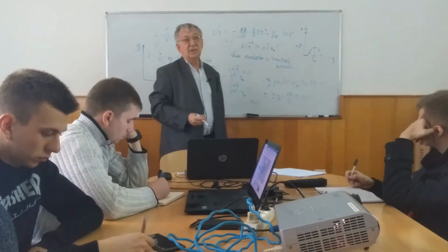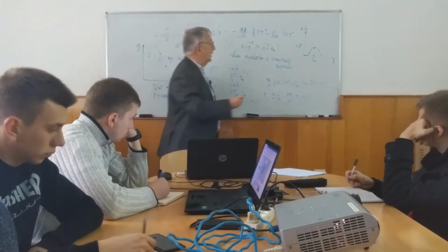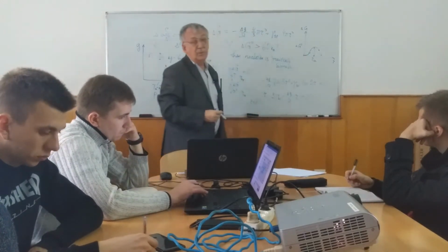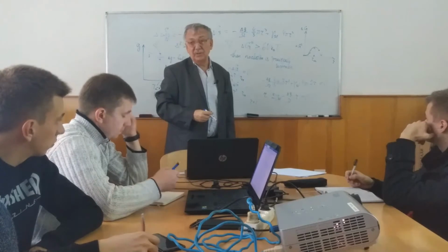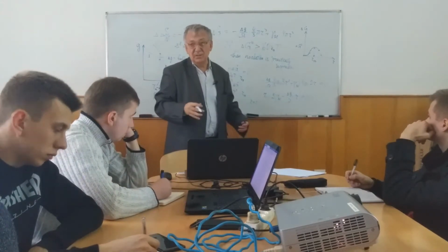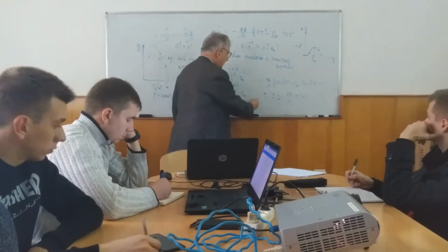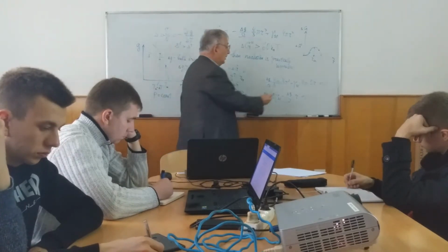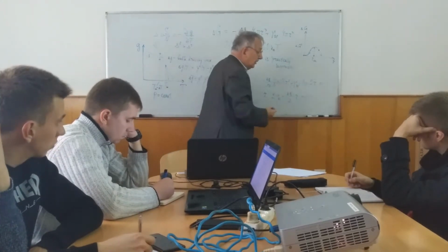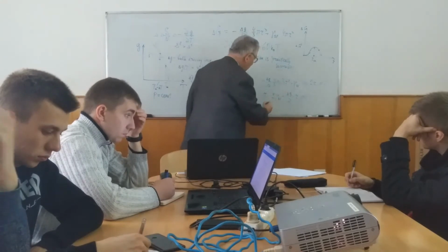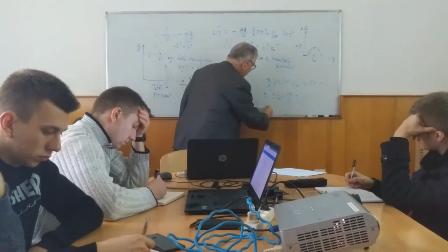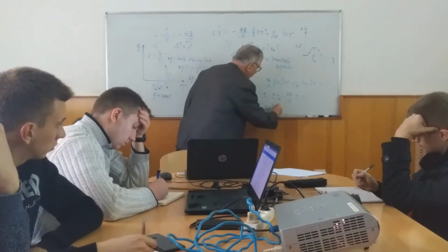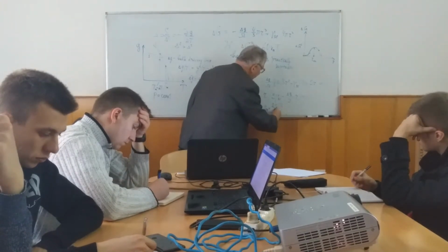Anybody of you can take the second derivative, and you will see that here the second derivative will be positive, not negative. So it's not maximum, it's minimum. We are not interested in minimum. So this is not physically interesting for us. And the second root of this algebraic equation is, of course, well known: R critical equal to 2 gamma SL omega divided by delta G.